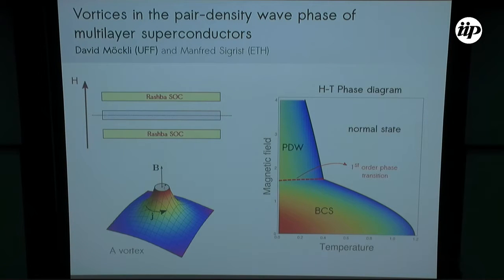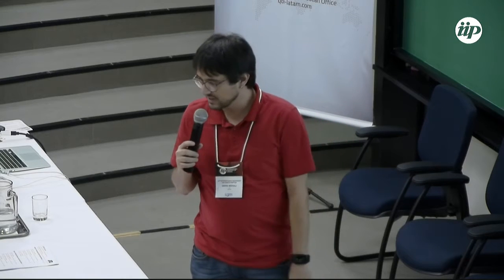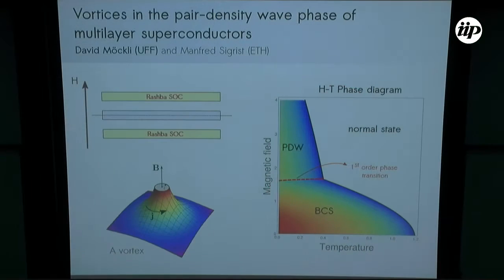Please. Good evening. This is theory motivated by some experiments on artificial Kondo superlattices. These are very complicated, strongly correlated systems. But this theory has very, very simple ingredients, and they are the following. Three identical superconducting layers. They are strongly Pauli limited by a perpendicular external magnetic field. Because of the symmetry of the system, the outer layers experience Rashba spin-orbit coupling, and the layers communicate. This apparently simple system displays, in my opinion, this amazing magnetic field temperature phase diagram.